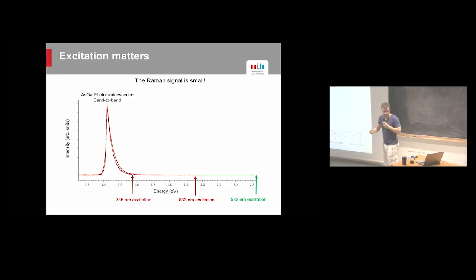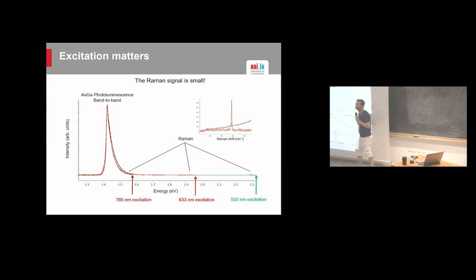Yeah, so this thing doesn't work anymore. So Raman is here. Okay? So that's this, that, and this. So if you now plot this as a Raman shift, meaning as an energy difference between incoming and outgoing photon, then you realize that those very small peaks, they do superimpose. So this is the Raman mode that I'm looking at.